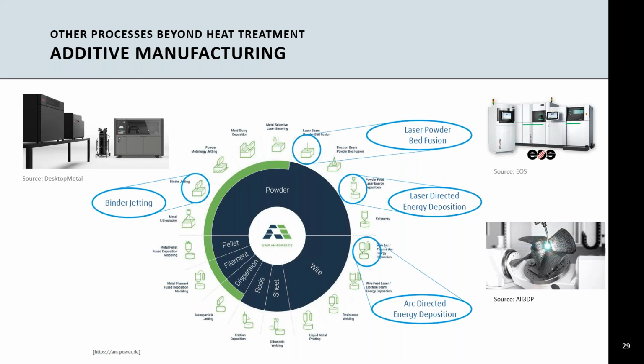As in MIG or MAG welding, metal wire is added to the electrode, melts in the arc, and the droplets form layers on the substrate. Processes with lower heat input, such as controlled short circuit metal transfer, are preferred given the heat sensitivity of most materials in additive manufacturing. What will happen is it could actually cause warping if it gets too hot, and that makes it more difficult to build layer upon layer. The shield gases protect the layers against the ambient air.